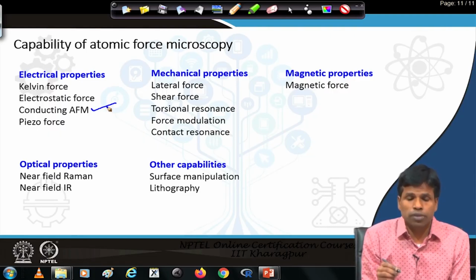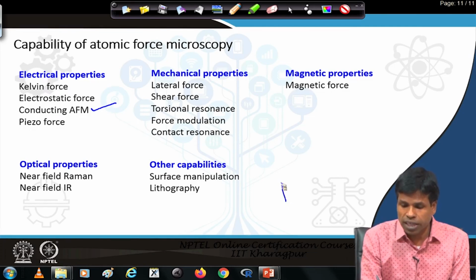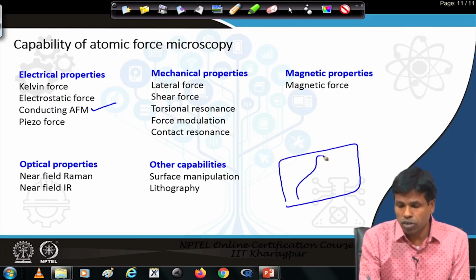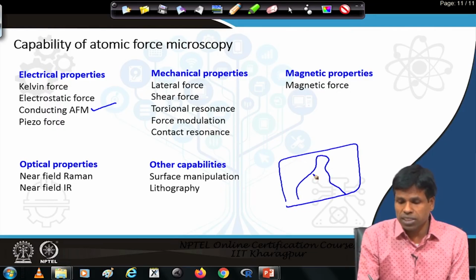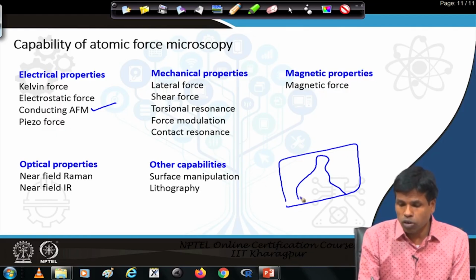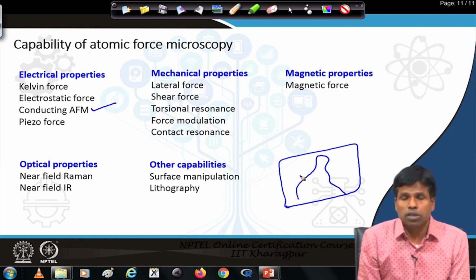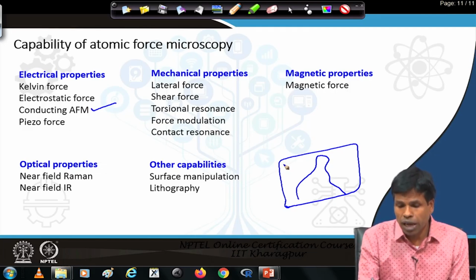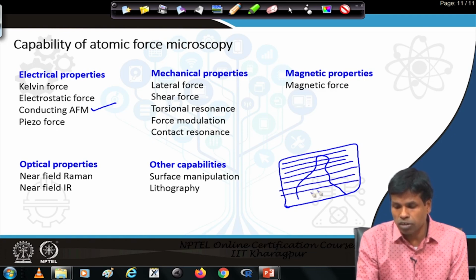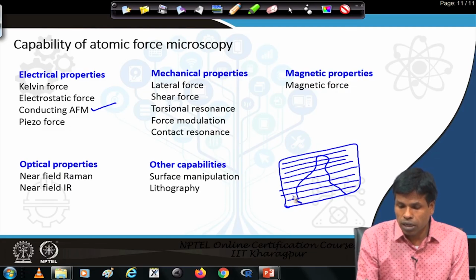But if we want to study the electrical properties of a sample, or let us say on any insulating substrate we have conducting wires placed in a particular manner, or this kind of conducting layers is present in the sample with a particular distribution or arrangement, then we can use a conducting tip and measure the current passing at different regions across the sample and get information where this conducting layer is present on the sample.